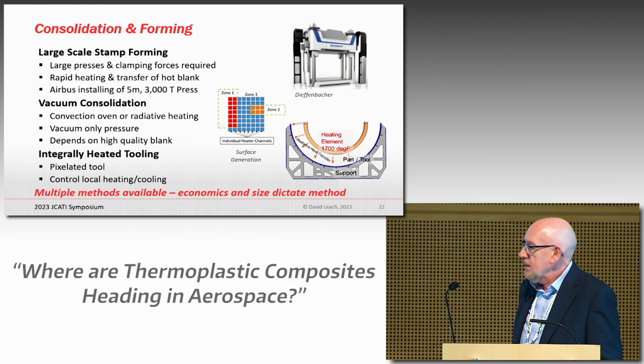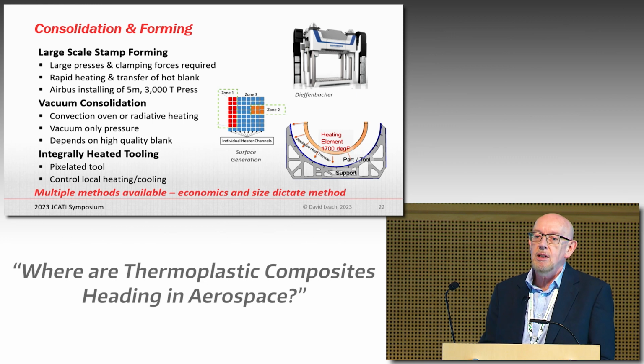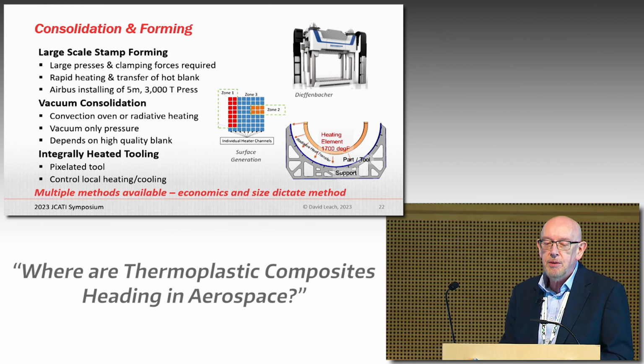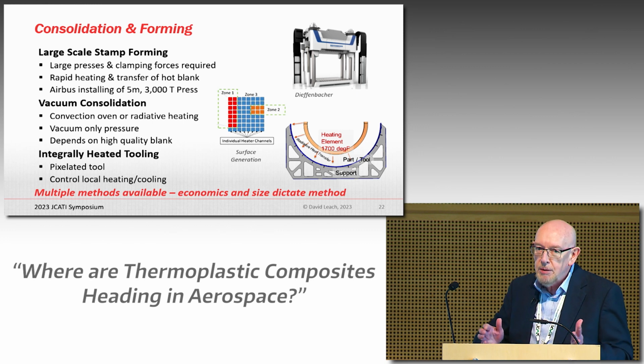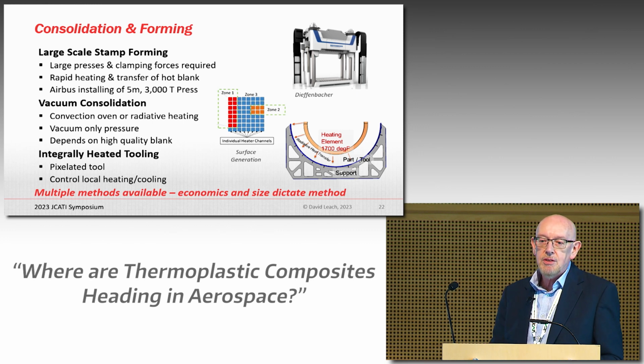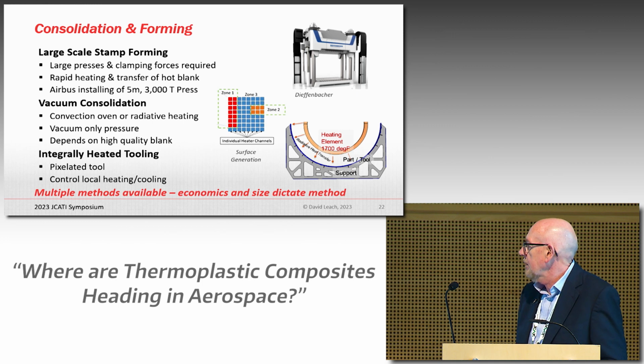This again depends on having a pretty high quality blank to start with though, because by definition, if you're only doing it under vacuum pressure, you don't have a big driving force to move that viscous polymer. So you need to have, again, a pretty low porosity blank, a pretty well consolidated blank to start with. But again, that can be a very economical process.